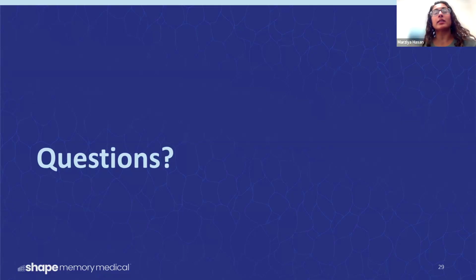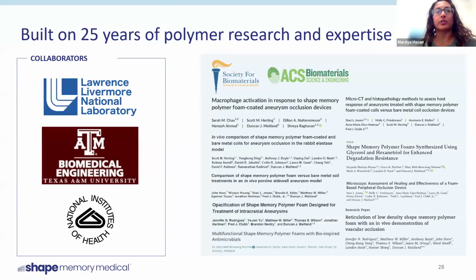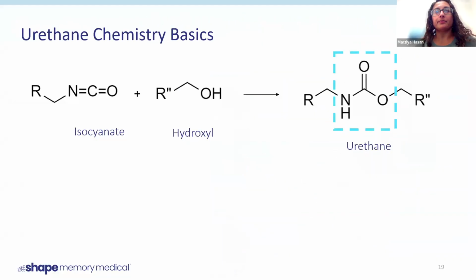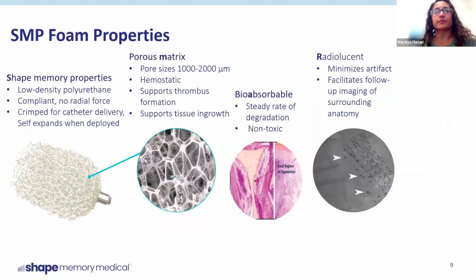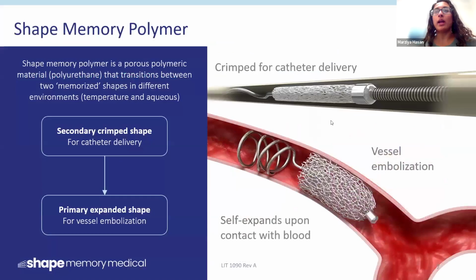No, so our devices, once they're deployed in the body, they're still in a crimped state. What will happen is we will deploy a device that's in this crimped state into whatever vasculature it needs to be. While it's in the catheter, the foam is not really being exposed to a lot of water, and it's not being exposed to the higher body temperature. But once it's out of the catheter, water molecules will start penetrating the polyurethane network and start disrupting the hydrogen bonding, which will then drive down the glass transition temperature. And once that transition temperature goes down below body temperature, then the material sees the body temperature as the heat stimulus that it needs to expand.